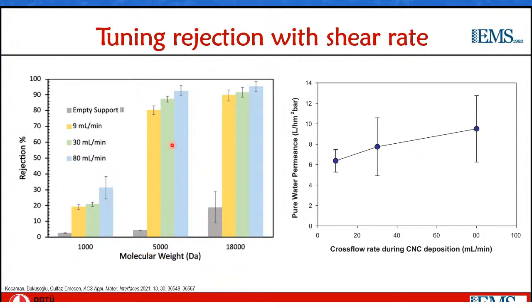However, for the larger probes, we see an increasing rejection with increasing shear rate, which is more pronounced for the middle probe, which has a partial rejection, and that is actually quite expected, since this is only partially rejecting. Any difference in the membrane pore structure will be reflected more in the rejection towards the probe. So indeed, it seems that we can align the cellulose nanocrystals with shear on the membrane as expected, but also this higher degree of alignment results in more and more compact deposits that increases the rejection of the membranes to the probe. So this provides a simple means of controlling the membrane structure by tuning easily adjustable fabrication parameters.